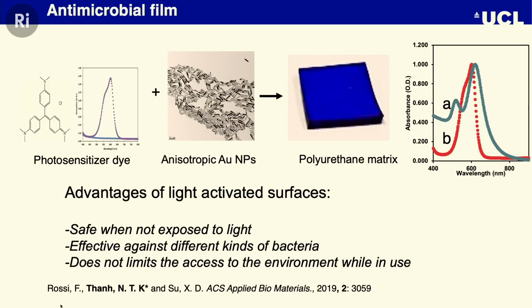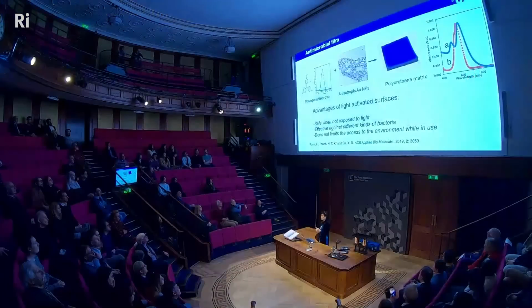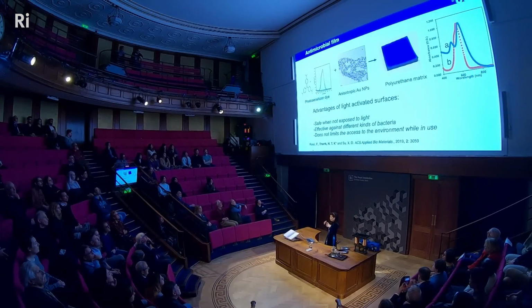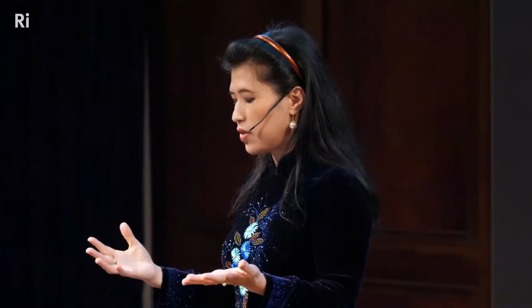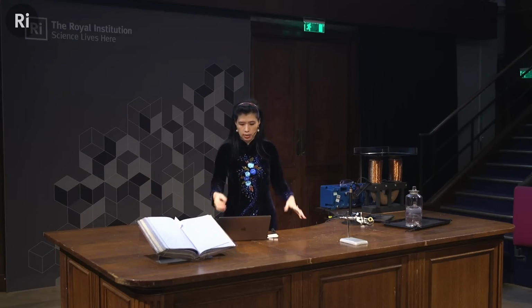So what is the practical use of that? You have the dye, called CV, crystal violet, and you put it together with the gold nanorod, and you embed it into a polymer film. But it's really important that you choose the gold nanorod at the right aspect ratio. So we choose something short and fat. So we make the absorption peak move to the lower wavelength, so that it coincides or overlaps with the crystal violet, so then you can have plasmonic coupling. And if you have this plasmonic coupling, you could really form ROS, reactive oxygen species, and you can kill the bacteria.